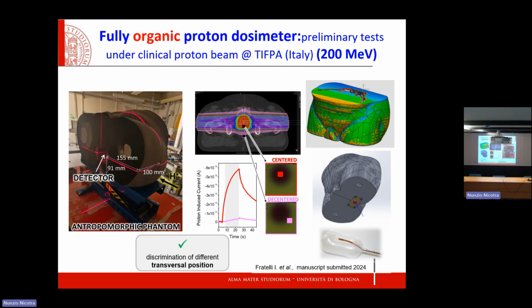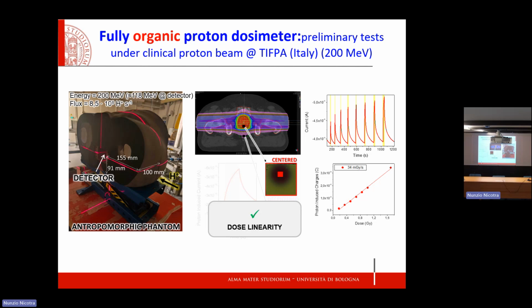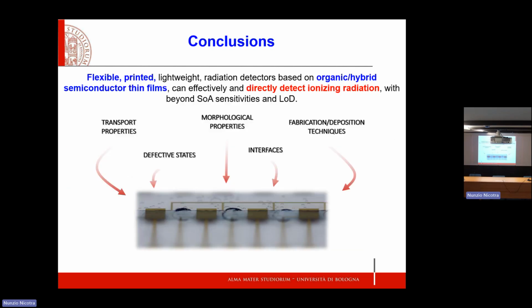This is the final test that we just finished doing. We used a dummy. This is a torso typically used for simulation that we tested at TIFPA in Trento, where they do irradiation with the 200 MeV protons, and we positioned our endorectal balloon exactly where it was meant to be in a proper cancer treatment, and we could assess that we could see when the beam was hitting the balloon and when the beam was not hitting the balloon, and that the response was proportional and linear to the dose received.